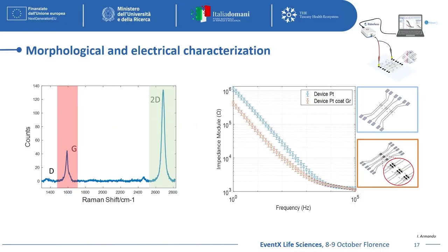We characterized the monolayer graphene using spectroscopy and microscopy. Based on Raman microscopy, we were able to appreciate the typical peaks of the CVD graphene monolayer, especially at 1,600 the G peak and at 2,700 the 2D peak. Then we also evaluated the conductivity of the graphene, and we observed that the device in which the electrodes are coated with graphene has a better conductivity.